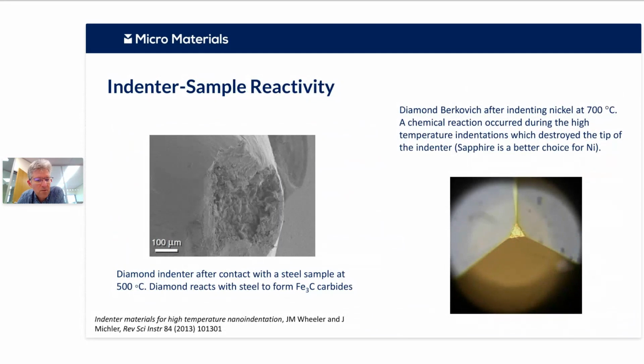The other thing that you do need to consider is chemical reactivity between the indenter tip and the sample, which may happen at high temperature, even if it doesn't happen at low temperature. So on the left there, you can see degradation of the diamond indenter after contact with a ferrous alloy, a steel sample, and with carbide formers, diamond indenters should not be used at high temperatures.